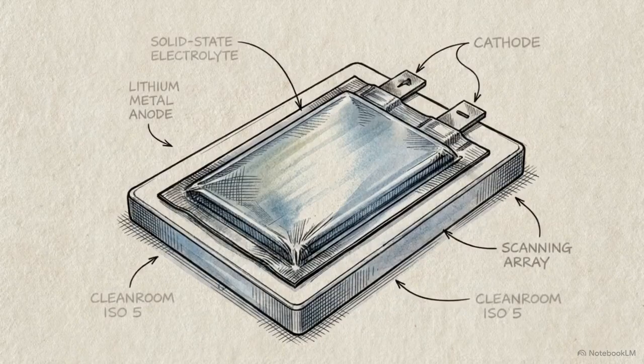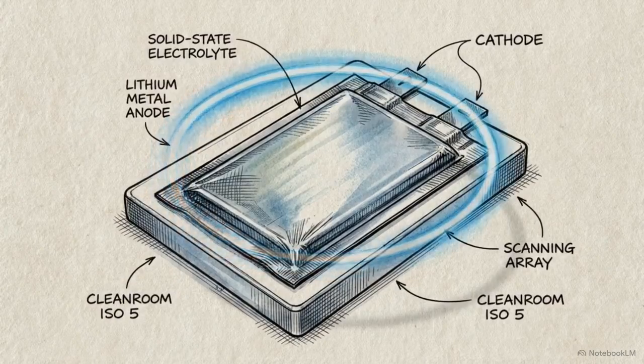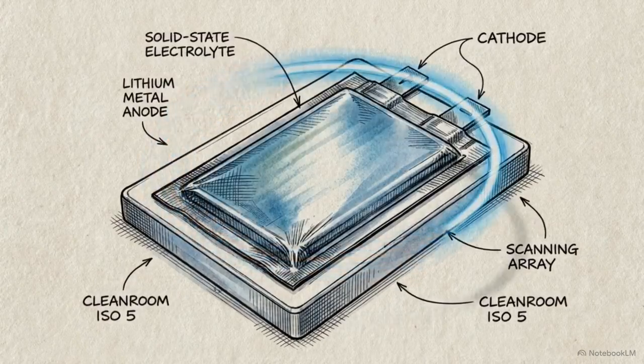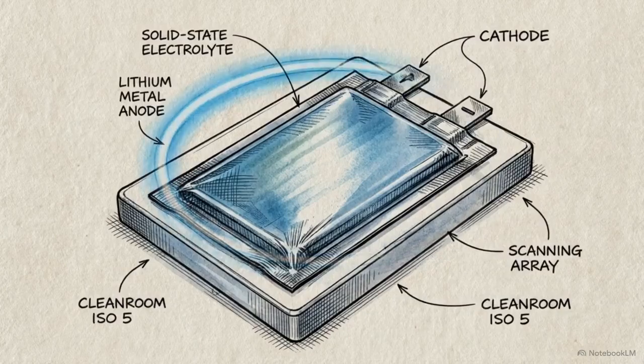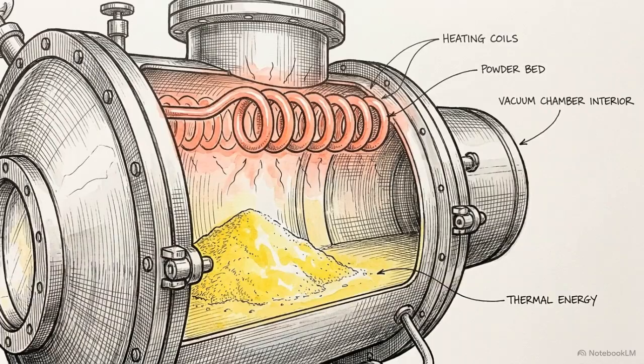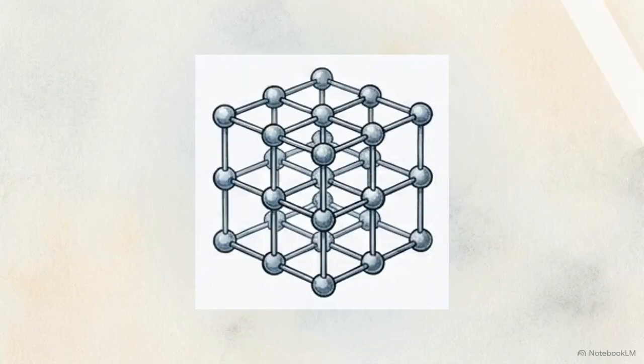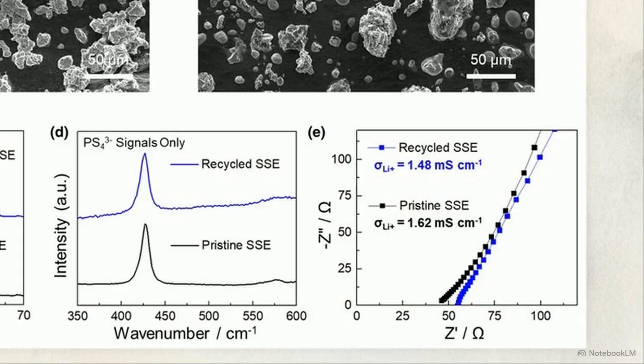The final engineering question is whether a directly recycled solid-state electrolyte actually performs to the same standards as a pristine one. After the ethanol is recovered, the sulfide solid electrolyte is thermally annealed under a vacuum. This direct regeneration step restores its pure phase and local chemical structure. This electrochemical impedance spectroscopy chart provides the empirical proof of that recovery. Looking at the Nyquist plots, the recycled blue curve tracks precisely with the pristine black curve, showing minimal deviation.